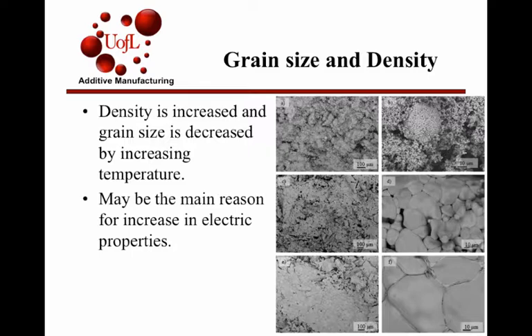And here are some SEM photos. You can see this will be your low temperature, this will be your high temperature, and then your middle temperature, and then your highest temperature. This is a zoom out shot and a zoom in as well. These are all the same magnification. So you can kind of see at the lower temperatures you have a lot more gaps in your material, and then as you get to the higher temperatures, it becomes a lot more dense. And you can understand how that would cause better conduction and better electrochemical properties in this material.